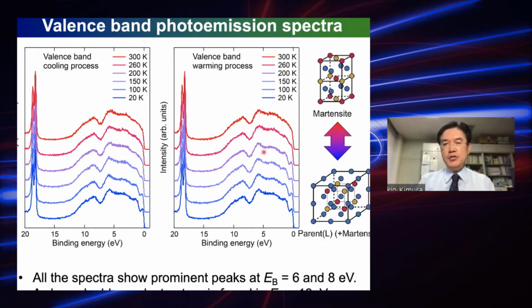In warming, you also see the change in the density of states near the Fermi energy, but there is a subtle difference between the cooling process and the warming process, which I will talk about later. First of all, the prominent peaks exist at binding energies of 6 eV and 8 eV. The other sharp peak is actually the core level spectrum from the gallium 3d photoelectrons. So we use this core level to normalize the valence band spectra at various temperatures.